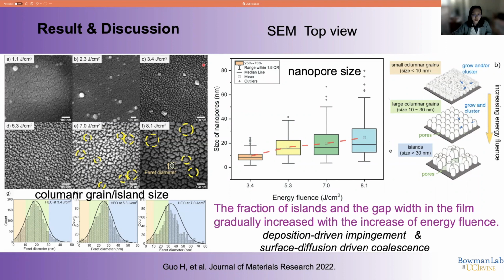The SEM images show the morphology of the thin films on the surface. You can see from low energy fluence to higher energy fluence, there are more obvious gaps or nanopores on the films. So the fraction and also the island size are increased with the energy fluence. From these two statistics, we can see the average size of the columnar grains and islands gradually increases. Also, the nanopore size also increases with the increase of energy fluence.